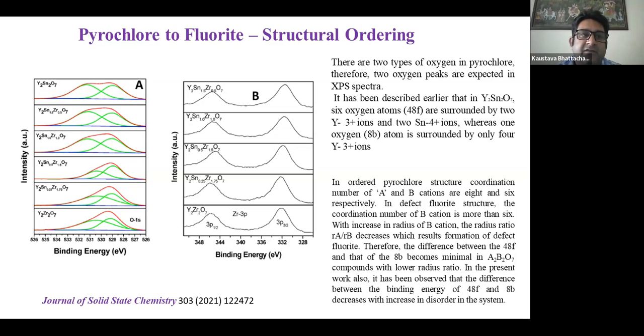Y2Sn2O7 is a complete pyrochlore structure, an A2B2O7. For A, the coordination number is 8. For B, the coordination number is 6. So it is a cubic and octahedral system. The oxygen present is of two types: 48f and 8b. The 48f has 2 tin and 2 yttrium 3+, whereas the 8b has 4 yttrium 3+. So there is definitely a difference in binding energy, and we can get two different types of oxygen here.